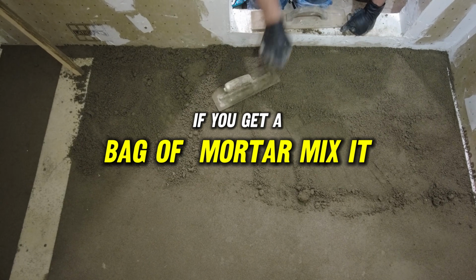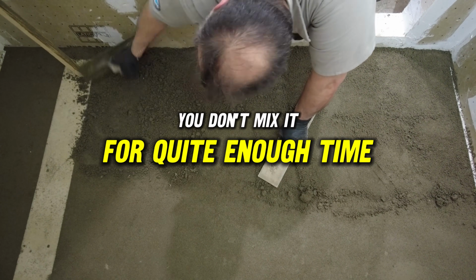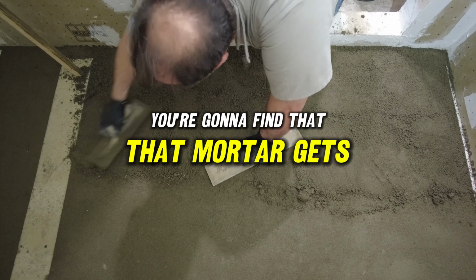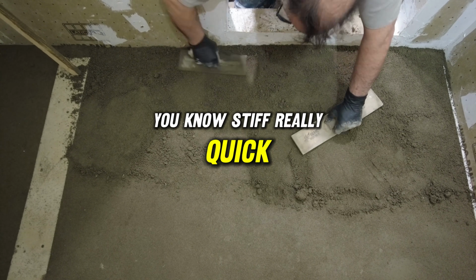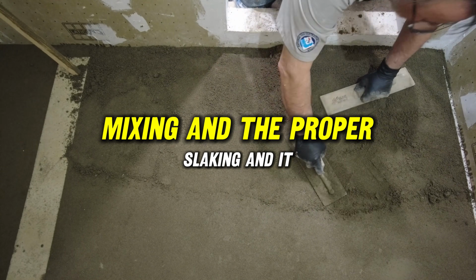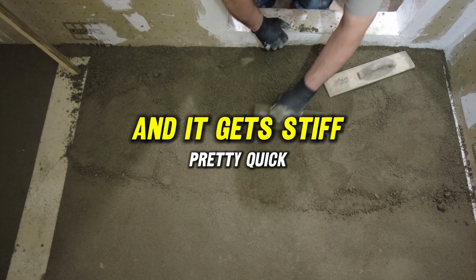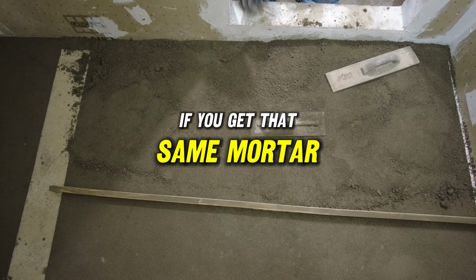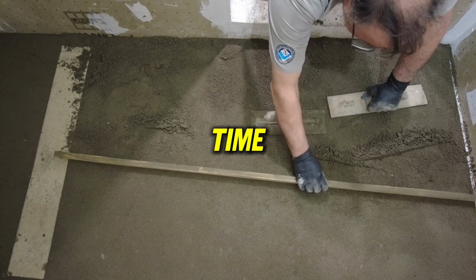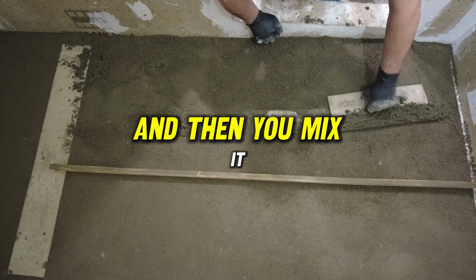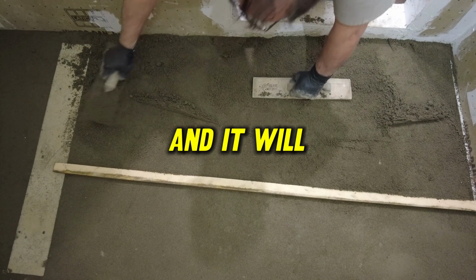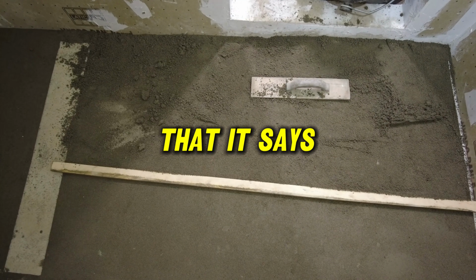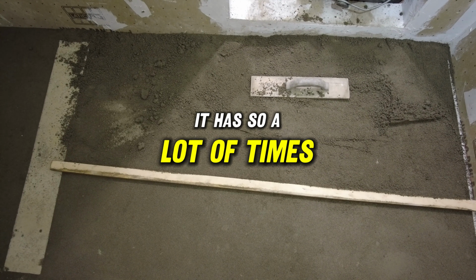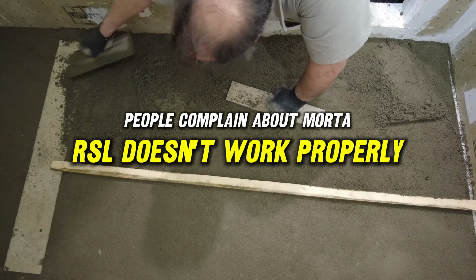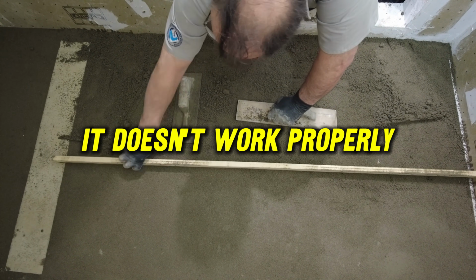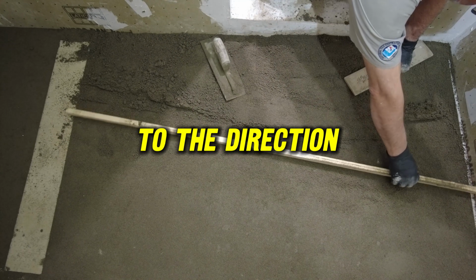If a bag of mortar says it needs to slake, make sure you slake it. If you get a bag of mortar, mix it, you don't mix it for quite enough time, and then you just start using it, you're going to find that mortar gets stiff really quick because it hasn't had the proper mixing and the proper slaking. If you get that same mortar, you mix it to the proper amount of time, and you let it slake the proper amount of time, and then you remix it, you're going to find it works much better, and it will have the properties that it says it has. So a lot of times people complain about a mortar that doesn't work properly. It's not because it doesn't work properly. It's because they haven't mixed it according to the directions. So that's another important thing.